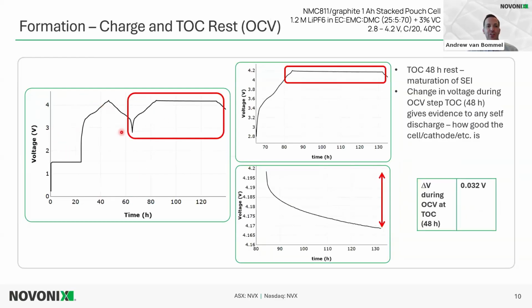After that first charge and discharge, we have a few metrics. We can see the dQ/dV to see that electrolyte reduction, but we can also see the FCE. And then afterwards, an important step is shown here. It's then charged, and during the top of charge, there's a rest step. This is where the cell is kept at open circuit voltage. If the cell is made really well, and there are not many parasitic reactions occurring, just some kinetic losses and some SEI growth, we can expect that this drop in voltage at the top of charge during the rest step, which is 48 hours, to be minimal.